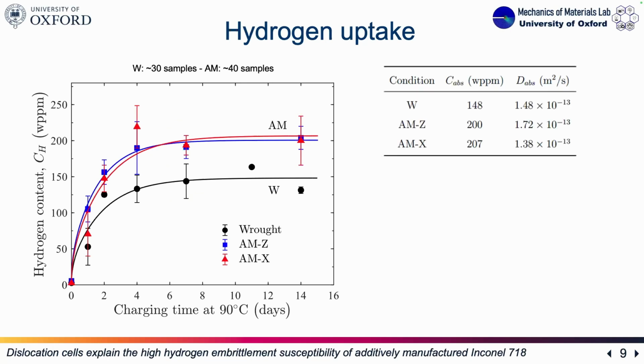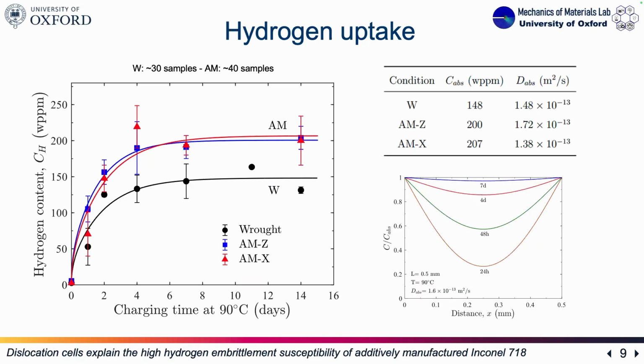Actually, only with this data we can already provide a value for the hydrogen diffusivity at this temperature if we do a very simple fitting. We see there is not a great difference in diffusivity, of course, at this temperature between the three conditions. Also, we see the directionality in the additive is not having a great influence. Actually, we can see the results are pretty comparable. But what we can say, as I already advanced in the previous slide, is that with this diffusivity we do a simple calculation of the hydrogen concentration profile. We see that from 7 days, we more or less have saturated the samples, which are very thin.